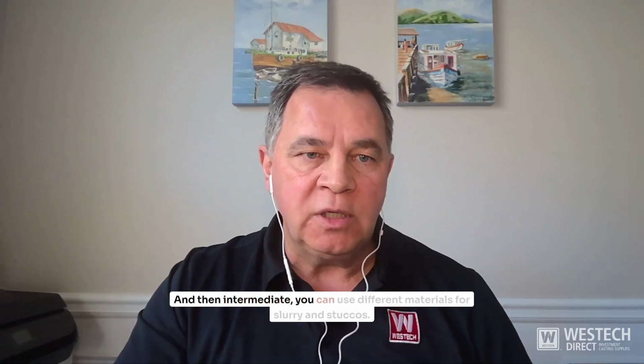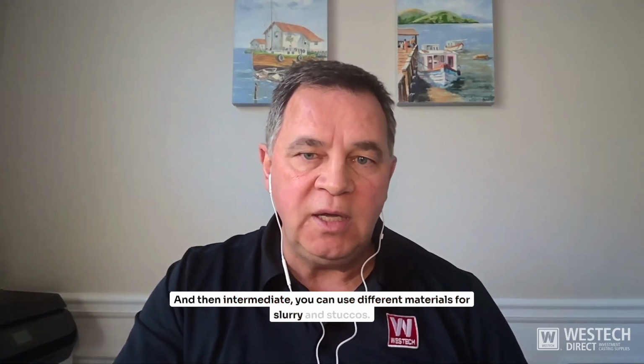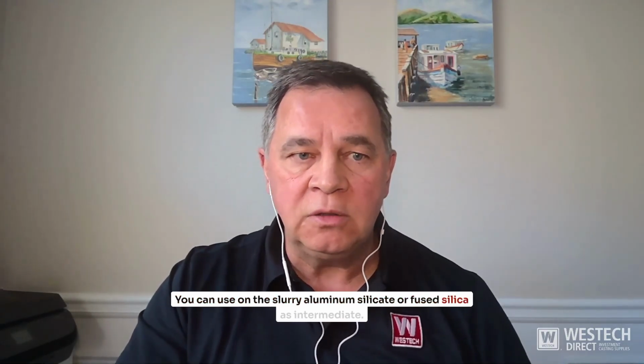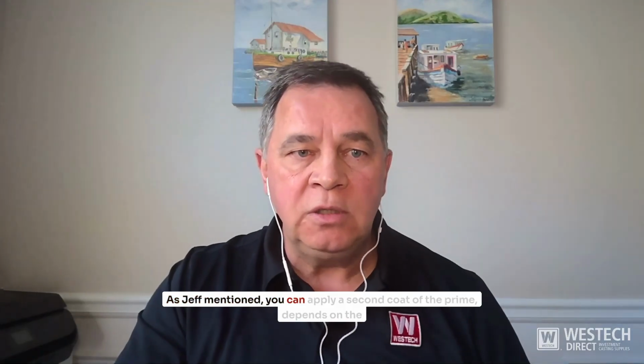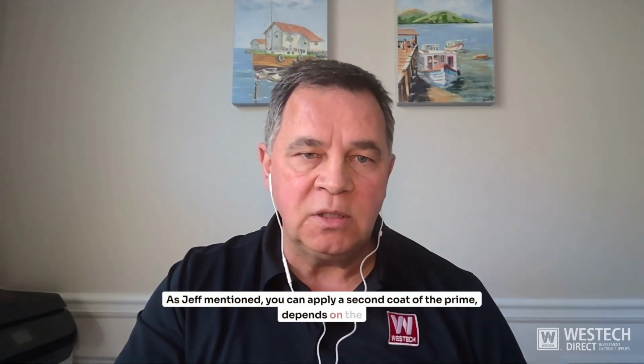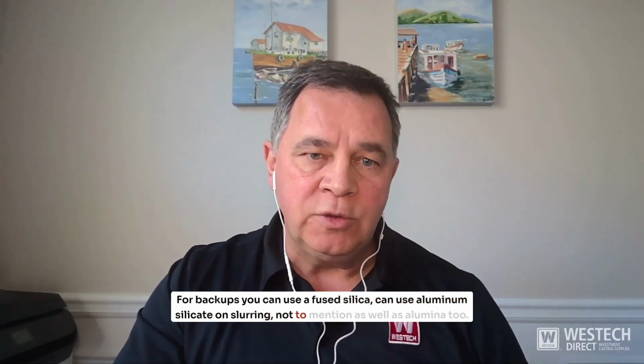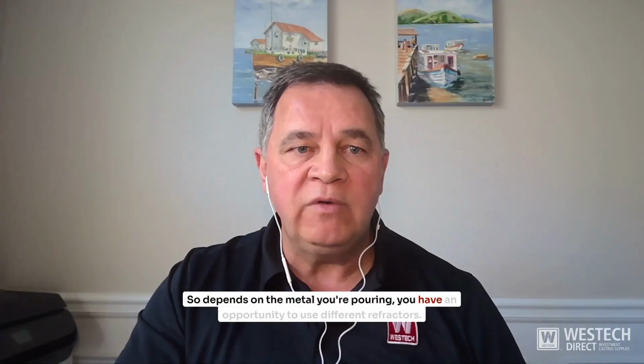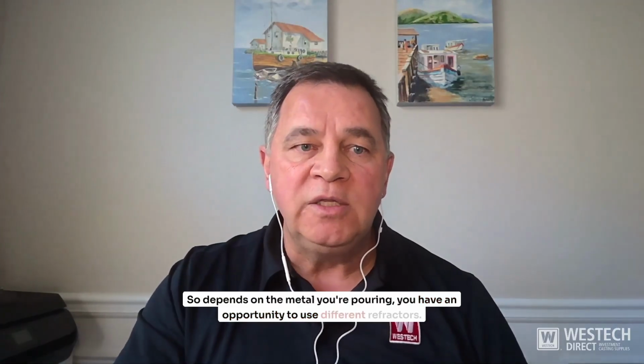And then intermediate, you can use different materials for slurry and stuccos. You can use on the slurry aluminosilicate or fused silica as intermediate. As Jeff mentioned, you can apply a second coat of the prime, depends on each company. For backups, you can use fused silica, you can use aluminosilicate on slurry, as well as alumina too. Alumina has much higher refractoriness for high temperatures. So it depends on the metal you're pouring. You have an opportunity to use different refractory materials for each slurry as well.